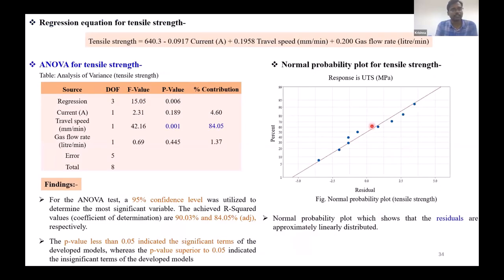And the regression equation for the tensile strength case works only for this particular 316L case, where the range is within the optimum range that we have selected, like 100 to 140 amperes. Only then can this kind of tensile equation be applied. And this shows that travel speed is having a major contribution in the tensile strength of this particular